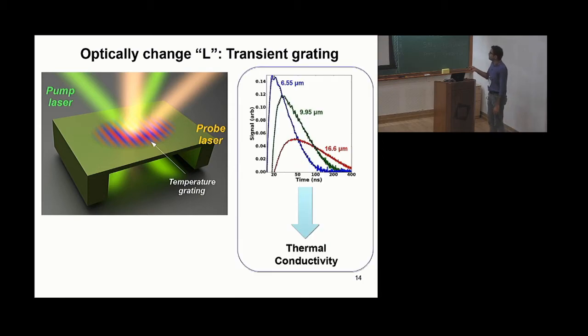Here, for example, are some of the example signals from the experiment. Initially, when you pump the system with the laser, you have optical excitation, which causes a temperature rise with time. Once the pump laser switches off, the heat accumulated as this sinusoidal pattern starts decaying. The decay rate gives you a measure of how fast the heat is being diffused out, which is basically the diffusion coefficient we want, or the thermal conductivity.